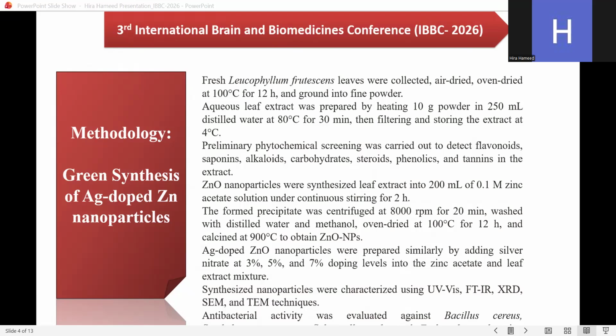Zinc oxide nanoparticles were synthesized by adding leaf extract into 200 ml of 0.1 molar zinc acetate solution under continuous stirring for 2 hours. The formed precipitate was centrifuged at 8000 rpm for 20 minutes, then washed with distilled water and methanol, oven dried at 100 degrees centigrade for 12 hours, and calcined at 900 degrees centigrade to obtain pure zinc oxide nanoparticles.